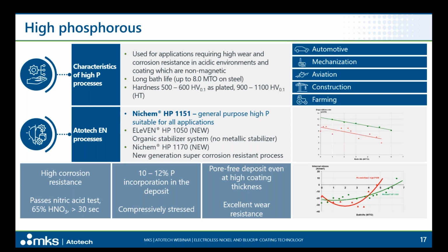As we can see on the right-hand side, these processes have a better deposition rate in comparison to the previous lead generation, and also much longer compressive stress over the bath life, until 6 to 7 MTO compared to 4 to 5 for the lead stabilized high P.